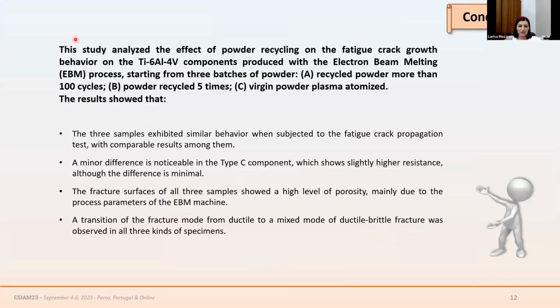So in conclusion, in this work, we analyzed the effect of powder recycling on the fatigue crack propagation behavior on these titanium components produced with electron beam melting. And these components were produced starting with 3 batches of powder. So we have the recycled powder more than 100 cycles, which is the type A, the recycled powder 5 times, which is the type B, and the virgin powder, which is the type C. And we saw that there were no particular differences between the 3 samples investigated, because all of these 3 samples showed similar behavior.